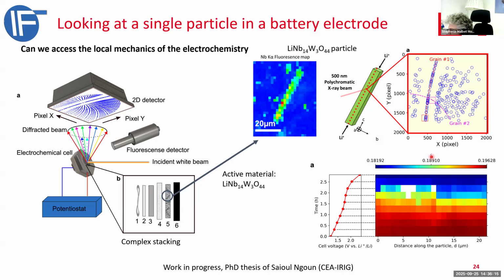So the c over a ratio, this is a strain along the c-axis, and you can see this with the time. At some moment, the strain is larger, the strain is changing a lot, and then at the end, the particle actually breaks into 3 parts, and then you can also follow the misorientation for all parts of this crystal, of this particle.